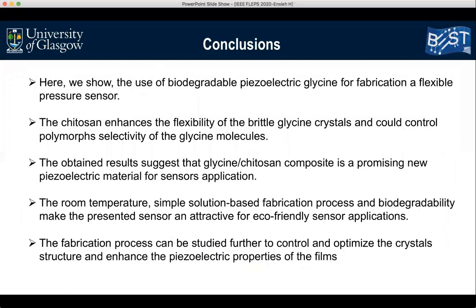So in conclusion, here we show the use of biodegradable piezoelectric glycine for fabrication of a flexible pressure sensor. The chitosan enhanced the flexibility of the brittle glycine crystal and could control polymorph selectivity of the glycine molecules. And the obtained results suggest that the glycine-chitosan composite is a promising new piezoelectric material for sensor application. And the room temperature simple solution-based fabrication process and biodegradability make the presented sensor an alternative for eco-friendly sensor applications.